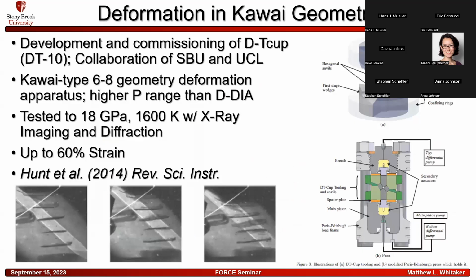So first we did the deformation Kawai geometry in the development and commissioning of the DT cup, which is the DT10. The 10 stands for 10 millimeters, which is the edge length of the cubic anvils that are used in the multi-anvil device. This was a collaboration between Stony Brook University and University College London. And this Kawai-type deformation apparatus did in fact lead to a higher pressure range than the D-DIA. We were able to get it up to 18 GPa and 1600 K with X-ray imaging and diffraction, and we were able to achieve a strain of 60%.